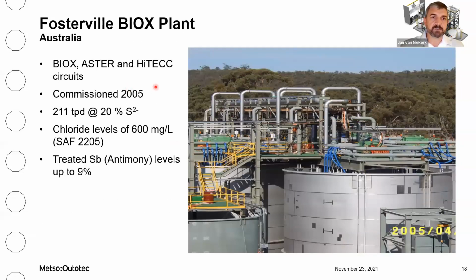The Fosterville plant in Australia was commissioned in 2005 and it has a design capacity of 211 tonnes per day of concentrate at 20% sulfur. It's interesting to note that this plant sees elevated chloride levels in the processed water and had to be constructed from duplex stainless steel for that reason. The plant also sees elevated antimony levels in the concentrate. Normal operating levels range between 3 and 5% antimony, but they can see up to 9% in the concentrate without affecting the BIOX performance.